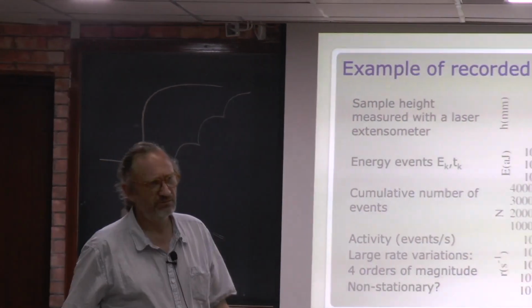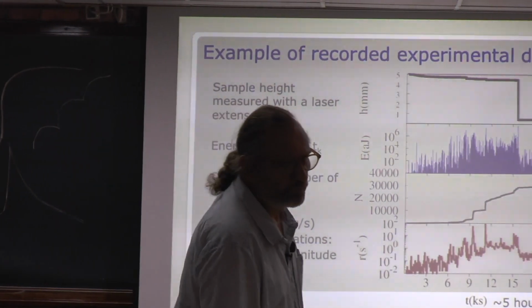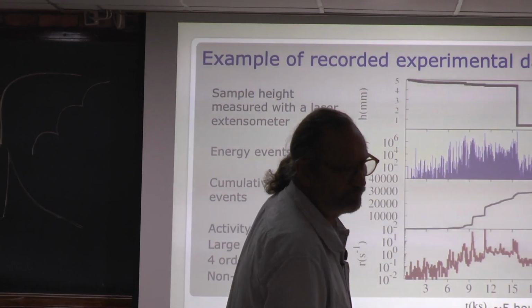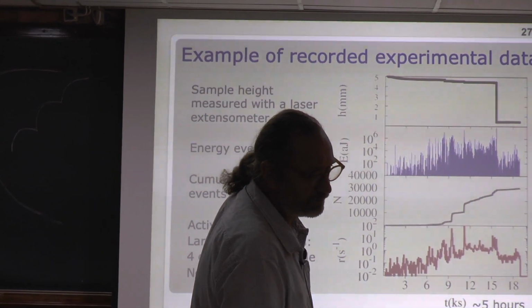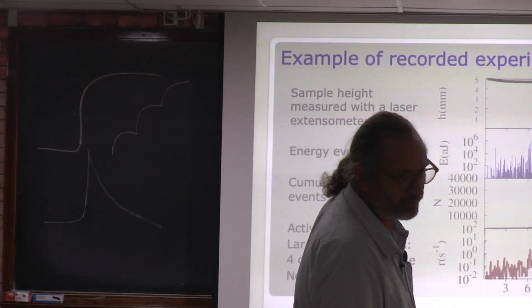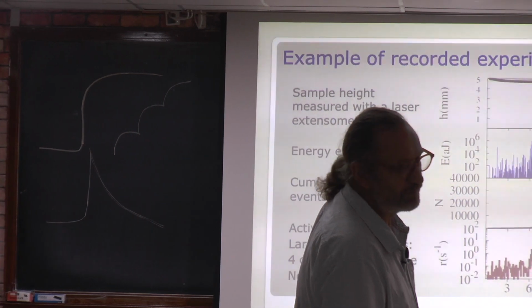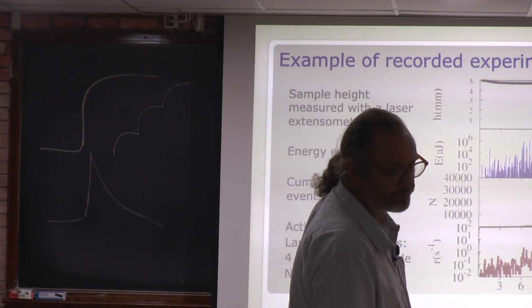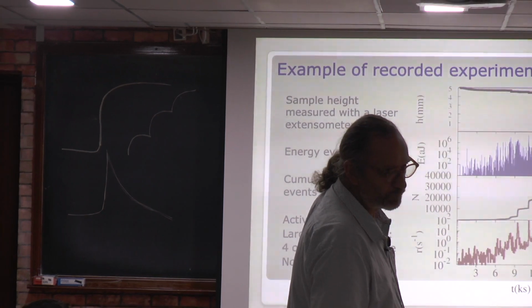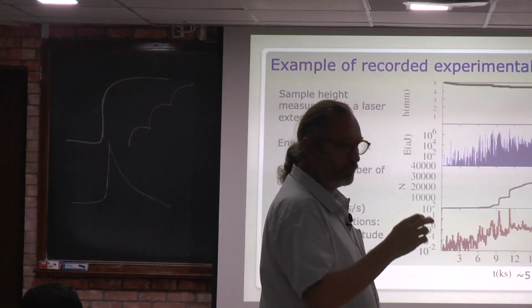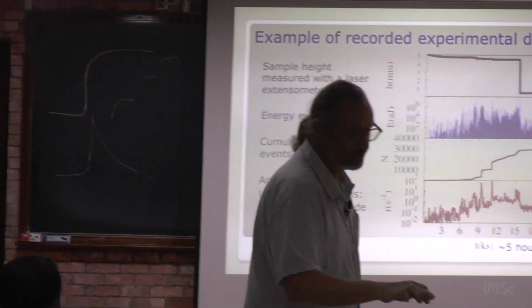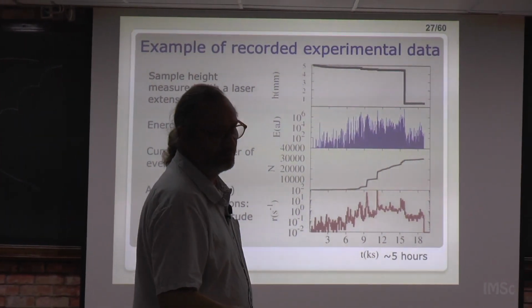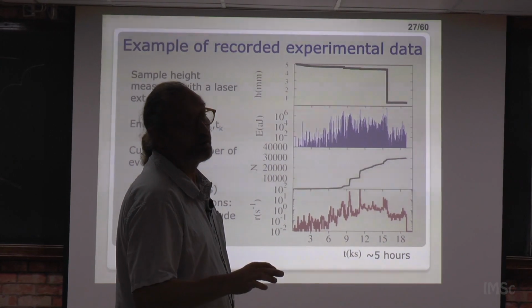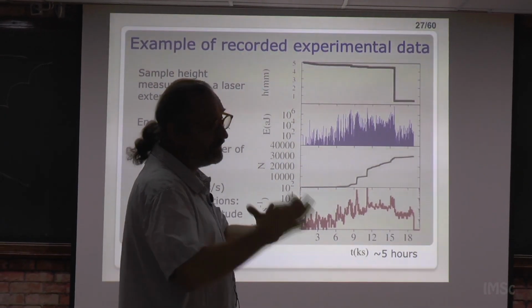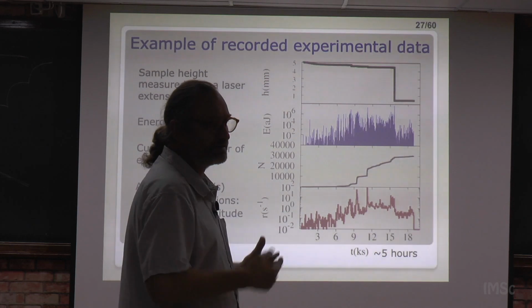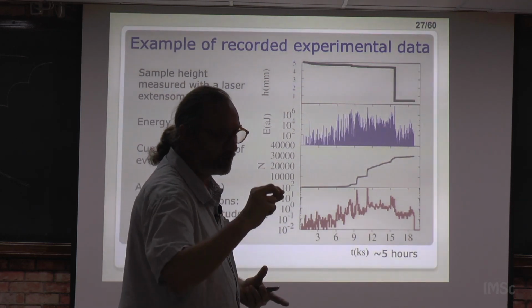My question is that all your materials are brittle or quasi-brittle. If I have to do with ductile metal, then in the plastic zone, where you have the non-linearity, should I see these avalanches there? We did nickel titanium metal, but porous. I see. Porous nickel titanium, so highly porous. It's a sort of mixture of what you are saying. What I am measuring is like a cumulative mixture of small events which are of your kind.